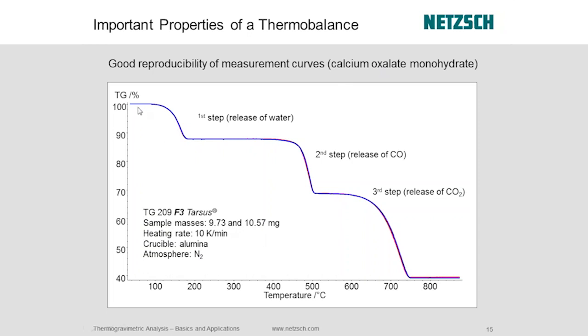And you can see that here's that stair step we talked about in the beginning where the mass changes. That's the release of water in the calcium oxalate monohydrate. And then with the second step, as we get up to around 500 degrees, we get the release of CO. And then around 600 plus degrees, we see the release of CO2. And then finally, we stabilize after it's gone.